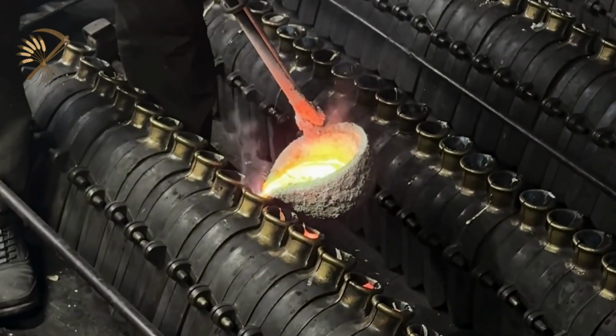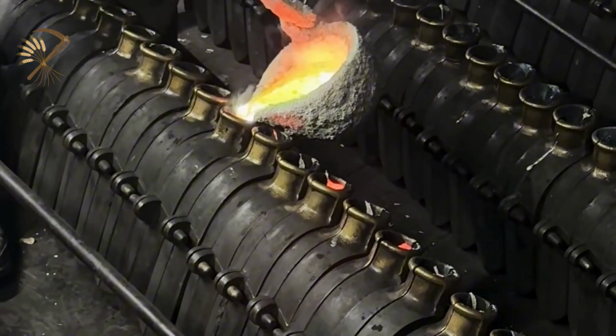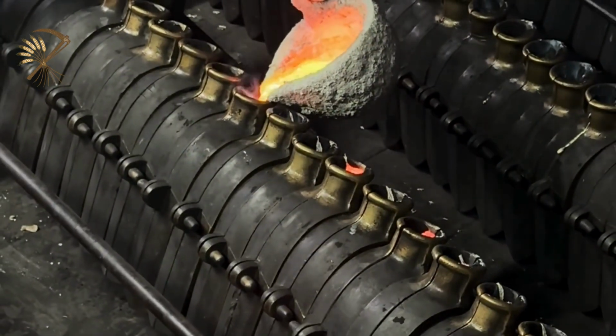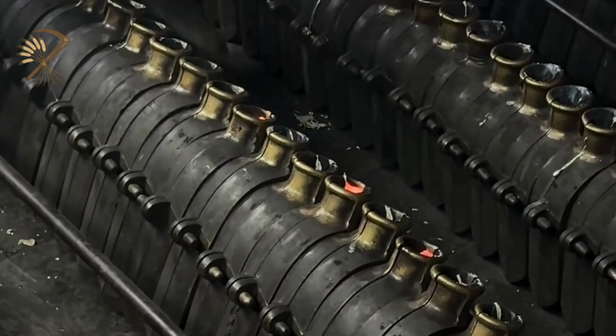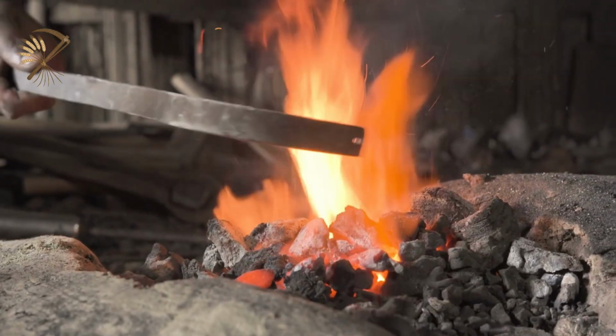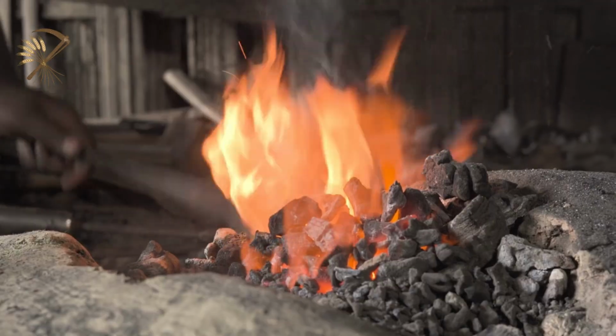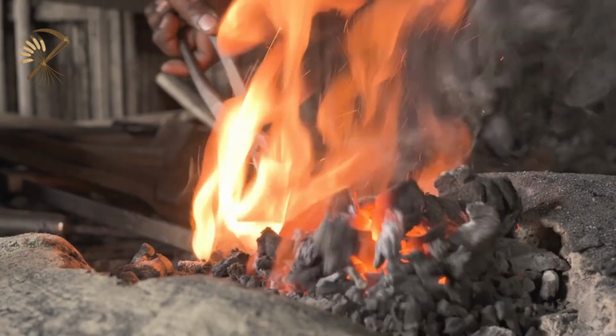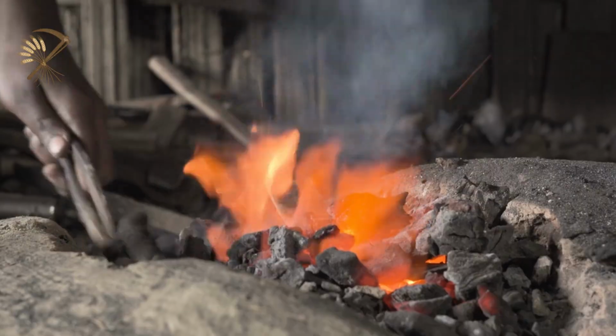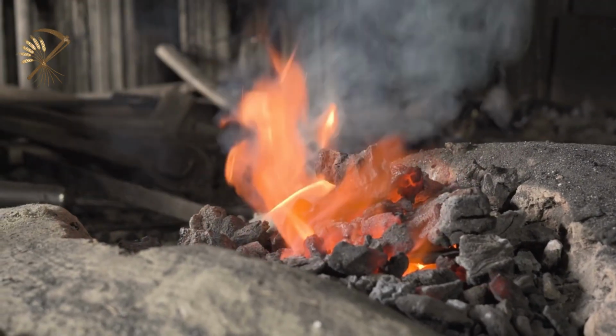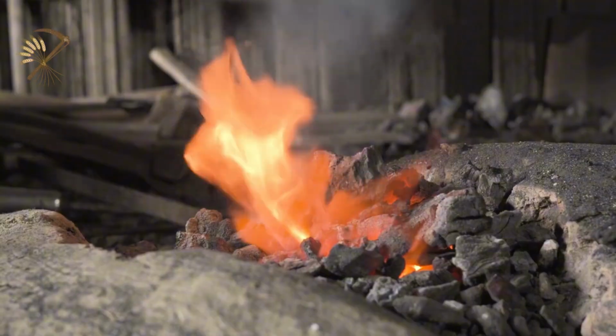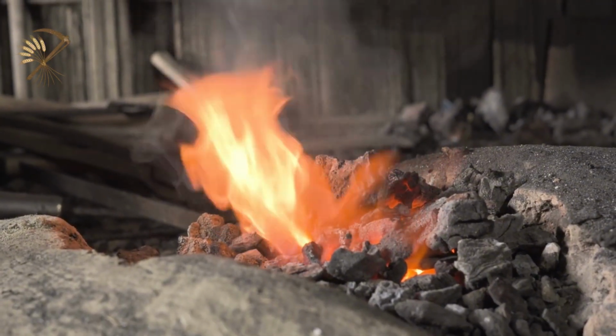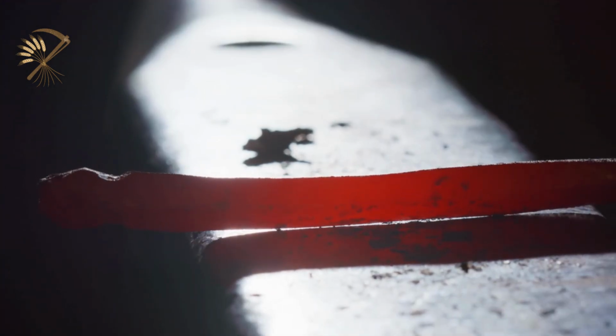Edge geometry. The cutting-edge geometry determines how well a tool performs its specific function. Each tool type requires different bevel angles optimized for the forces and materials encountered during use. The hoe blade requires a 25 to 30 degree bevel angle, steep enough to provide strength, preventing the thin edge from folding under the lateral forces of soil cultivation, but shallow enough to slice through soil with reasonable effort. The blacksmith files this bevel by hand, checking the angle with a protractor or practiced eye, working until the bevel is consistent from one end to the other.